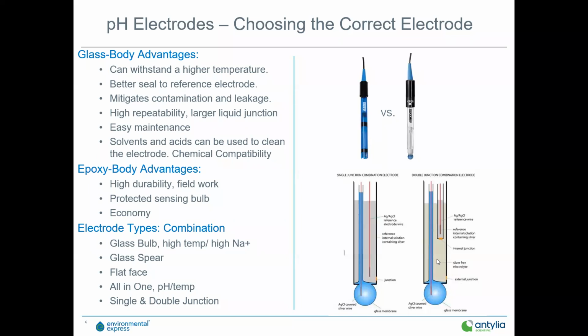As those poisoning ions can get into the electrolyte, obviously they're big. The metals are big and positively charged. That'll attack the chloride part of the reference tip. The phosphates, sulfates, nitrates, big and negatively charged, that'll pull off the silver ions. So what happens is these poisoning ions work their way through the electrolyte and will try to attack the reference tip. The double junction actually has, we've got a couple designs with the glass capillary tube. Normally they're not on the lower, it's actually on the upper side of this capillary tube. And the poisoning ions have to go all the way up and around back to get to the reference.